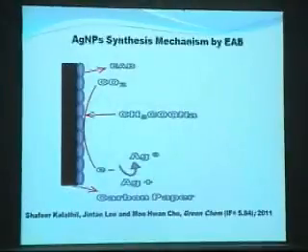So we produced silver nanoparticles using electrochemically active biofilm. You can see a graphic. We just used a carbon paper, and carbon paper is just a support for the biofilm. You can see the carbon paper and the electrochemically active biofilm stuck on the carbon paper, and we used sodium acetate as an electron donor. Here we oxidize sodium acetate to electrons. Normally these electrons are highly reducing in power, so these electrons will rapidly reduce the silver ions in the solution, giving nano size. So this is a new mechanism for synthesizing nanoparticles using electrochemically active biofilm.